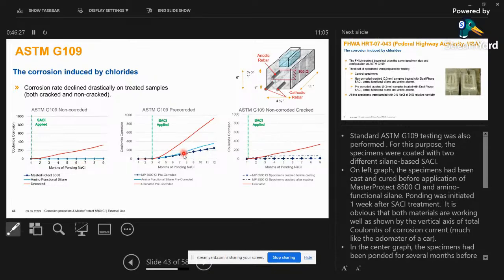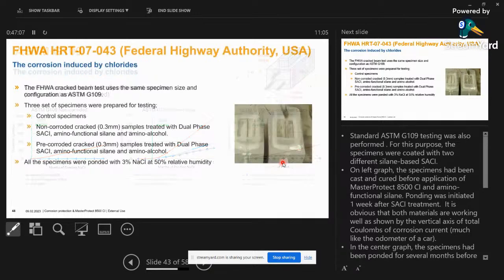But when it comes to pre-corroded structures, you will see that the bottom part, which is a dual phase penetrative corrosion inhibitor, gives much better results compared to the amine based. The result is the same even in non-corroded but cracked structures. So you've got cases where the structures are cracked, and if you have to understand how the corrosion activity is happening, this is found to be better compared to the other type of silanes or of the other type of surface applied corrosion inhibitors.